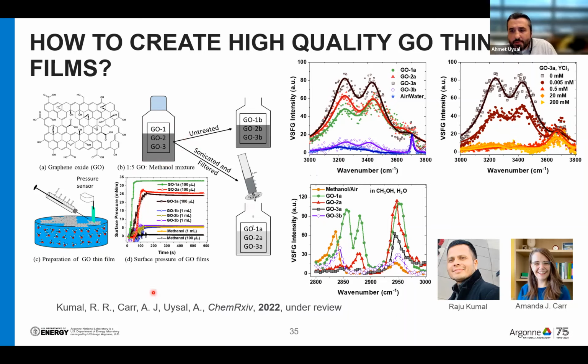And we have described it in this preprint if you're interested, but I won't go into details. I will just show one piece of data that we obtained with this system. With these high quality films, now we can look at the graphene oxide water interface very nicely using SFG and reflectivity again. And here we see something very interesting as we adsorb yttrium to the graphene oxide surfaces.